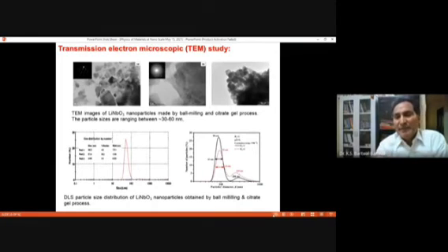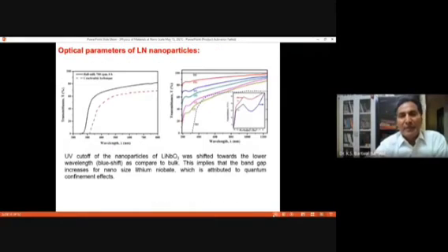You have to have the size of those particles, where the size falls. So it comes from this, I think it is 30 to 60 nanometer. It is much below the 100 nanometer. So for any device, if you have a size between 1 nanometer and 100 nanometer, you can use that material for a device application.